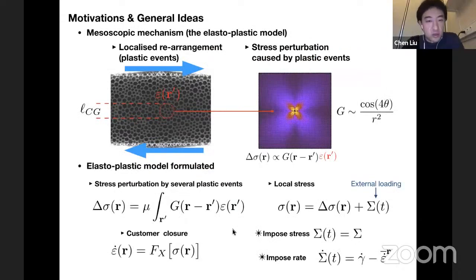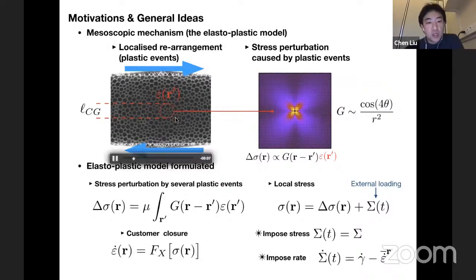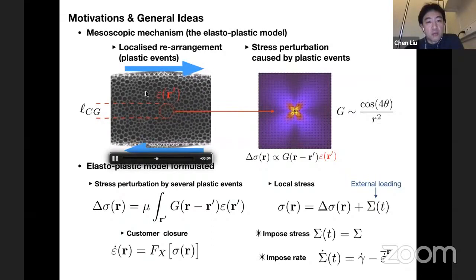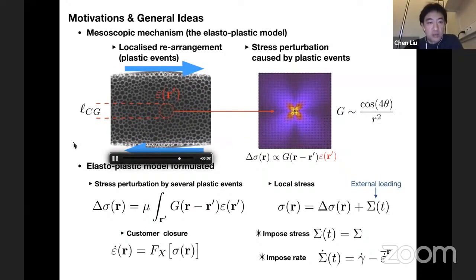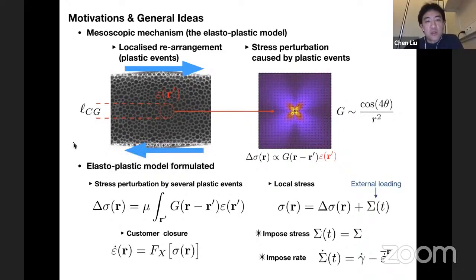And then I'm going to introduce our current understanding or knowledge about the plasticity of this kind of material on the mesoscopic scale. This is the work originated by Argon in the mid-70s, which is called the local plastic events. So for example, if you take a foam system, you shear in this direction indicated by the blue arrows. What happens is that you can see during the video that the macroscopic deformation is updated by the very localized rearrangement of particles, which we call plastic events. And these events happen in a typical size, I will call it a coarse-grained length scale.